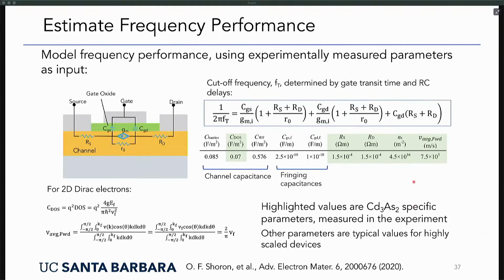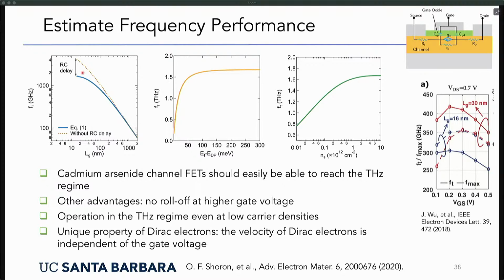So you can take these measured parameters that I just showed you and estimate what the frequency behavior of a device that uses cadmium arsenide as a channel should be. There is a circuit model here for a MOSFET type of device, where we have a gate dielectric, and orange is the cadmium arsenide channel. I just gave you numbers for the sheet resistance. We can calculate the velocities from the data I showed you, along with the sheet carrier densities, and we can estimate the capacitance from the density of states. Putting all this together into the circuit model, this is what my student Omar did, to estimate what the cutoff frequency fT should be for cadmium arsenide. And these results are quite encouraging. You can see that this cutoff frequency reaches, even for small devices where RC delays are significant, into the terahertz regime.